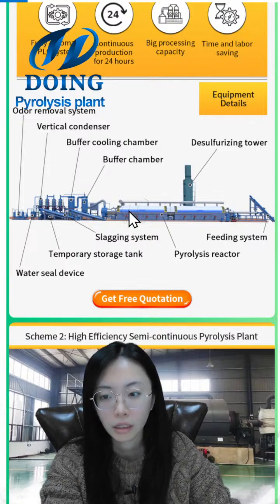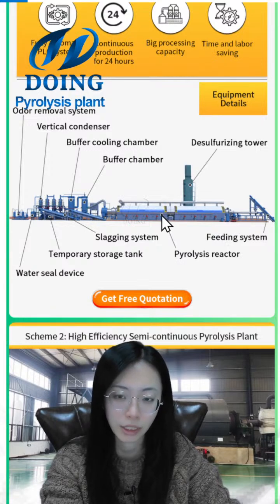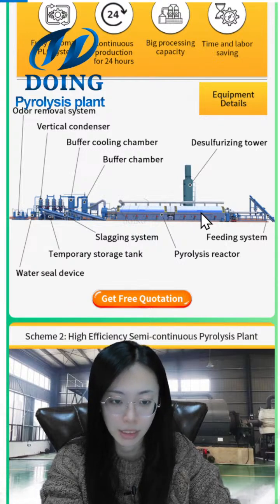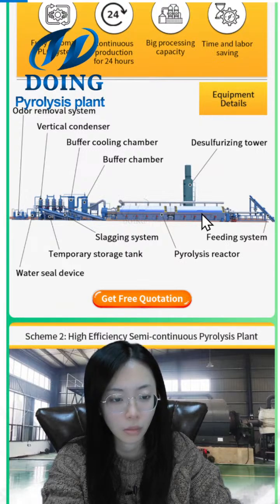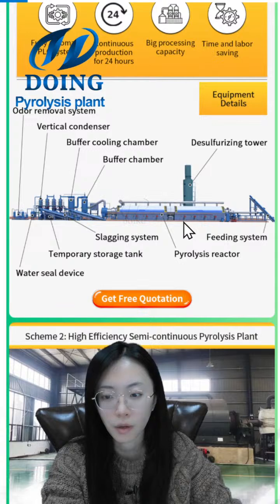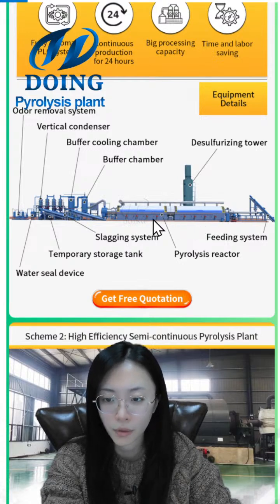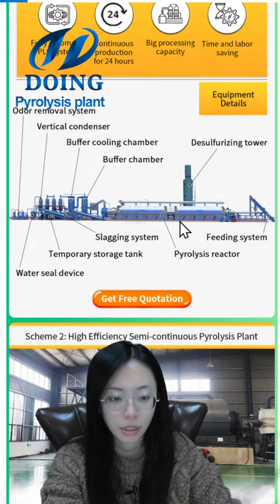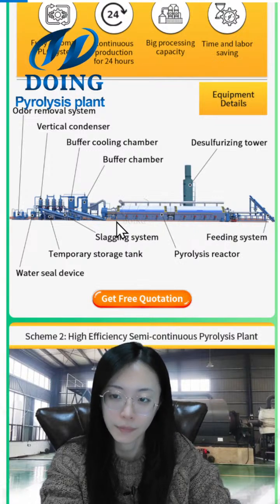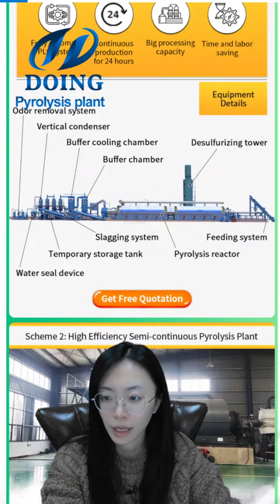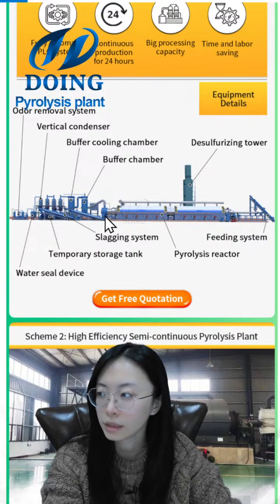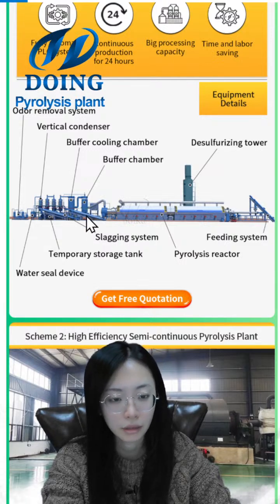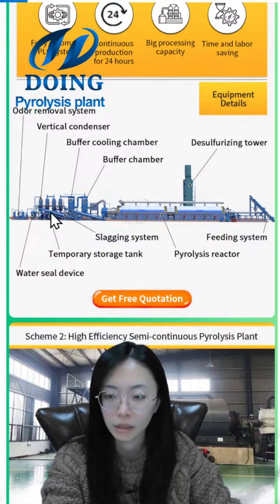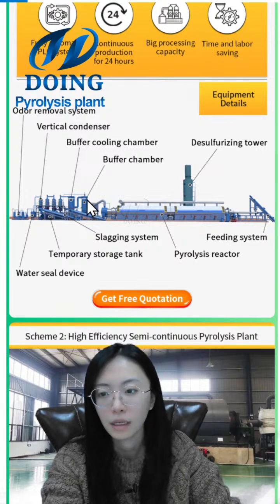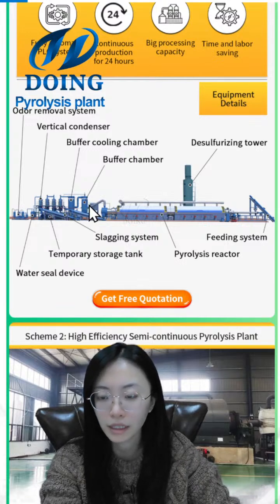That is the reactor. Outside is the installation cover, inside is the reactor to heat the raw materials. The working environment is non-oxygen and normal pressure, and in this environment, this red point is the burner to heat. The heating temperature is nearly 400 degrees. And then this is the slagging system to slag the carbon black when we pyrolyze. The slagging system is the slagging winch, which has the water cover outside, so we can cool down the carbon black at the same time we slag them. Then we can pack them directly after slagging. And this tank is all the condensation system.